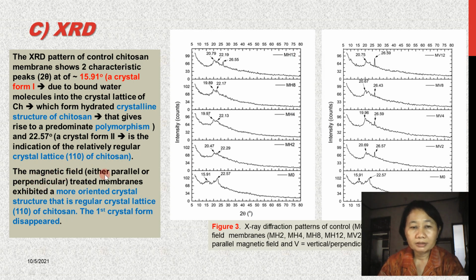The magnetic field, either parallel or perpendicular treated membrane, exhibits a more oriented crystal structure, that is the regular crystal lattice 110 of Chitosan. The first crystal form disappears. It means all the membranes treated by magnetic field, either with the parallel direction or perpendicular direction, get an oriented crystal structure. It means only the second structure remains. The first structure disappears. The same thing with the membrane treated by the perpendicular magnetic field.